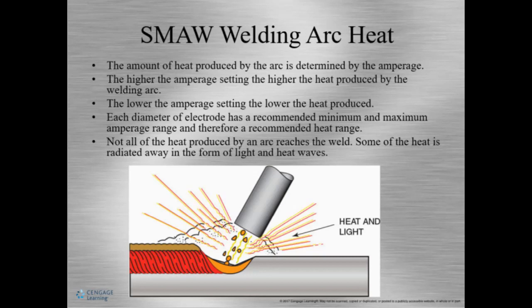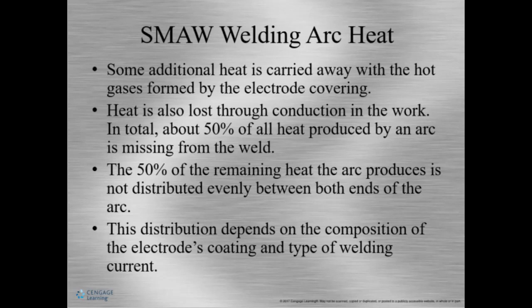So not all of the heat produced by an arc reaches the weld. Some of it is dissipated and radiated away in the form of light as well as heat. Some additional heat is also carried away with the hot gases. Okay? Heat is also lost through conduction in the work. So it goes into the work and disperses. So about 50% of all the heat produced by the arc is missing from the weld. Okay? The remaining 50% the arc produces is not distributed evenly. So it doesn't go to one side or the other. The distribution depends on the composition of the electrode's coating and the type of welding current.